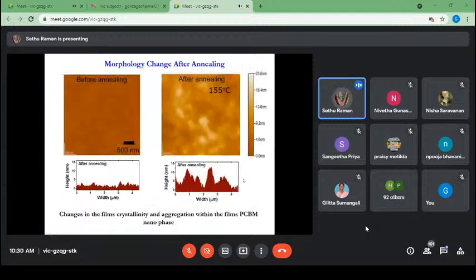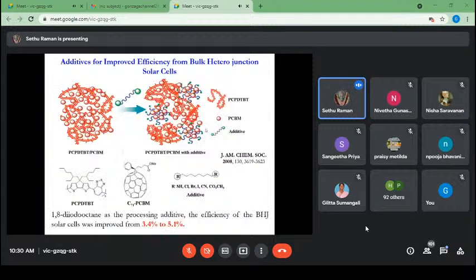So after annealing, what happened to the morphology? You see before annealing and after annealing, some phase separation is there, some changing of the crystallinity, and then aggregations of P3HT and PCBM in nanofibers. This will help to enhance the power conversion efficiency. This is the additive concept, additive for improved efficiency of bulk heterojunction solar cells. This work was reported in the year 2008.